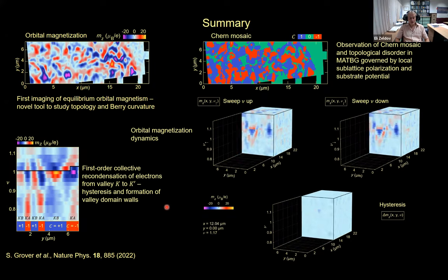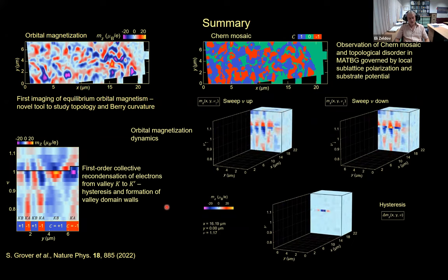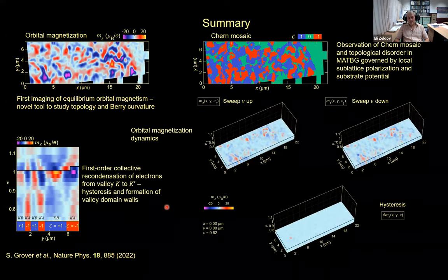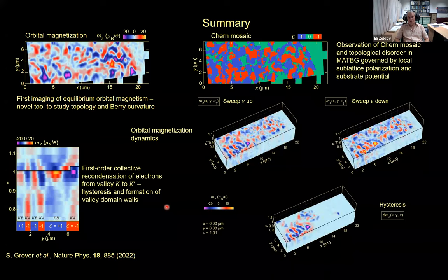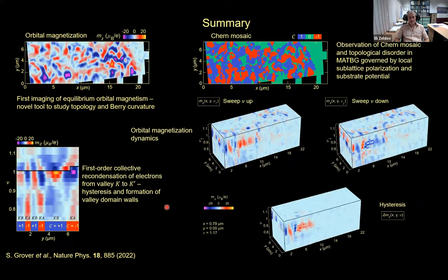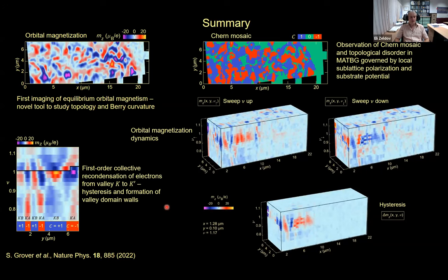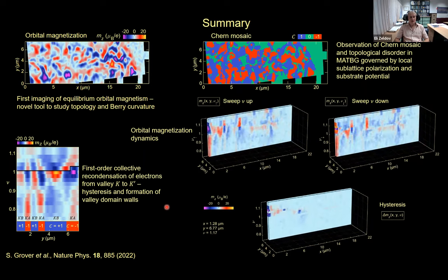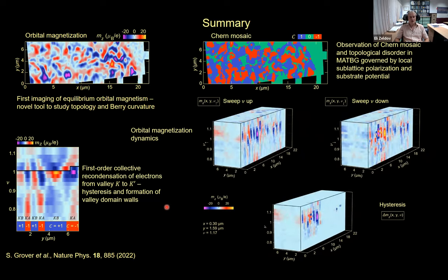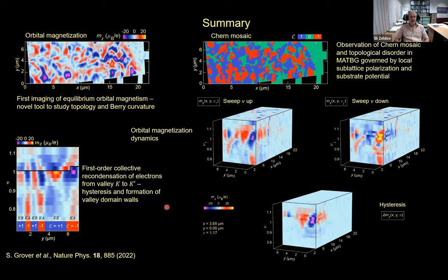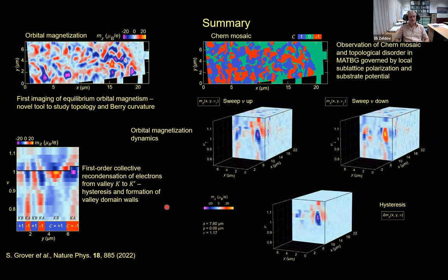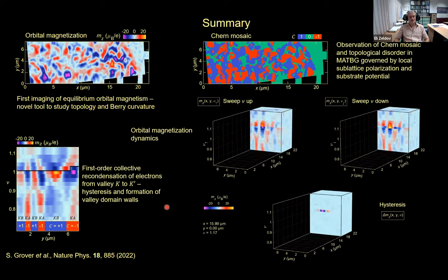And in fact, this particular sample, both by fabrication and by transport measurement, is not aligned. So it complicates matters even further. And I'm sure strain is an important factor. Twist angle disorder is an important factor. But eventually the system, if you are gapped, and we know that the bands are topological, has to decide whether locally it has a Chern number plus one or minus one. And it is not at all trivial that it should choose the Chern number of, let's say, plus one through the entire sample. On the contrary, there are very good reasons why it shouldn't do so. And I think this is the main message here.